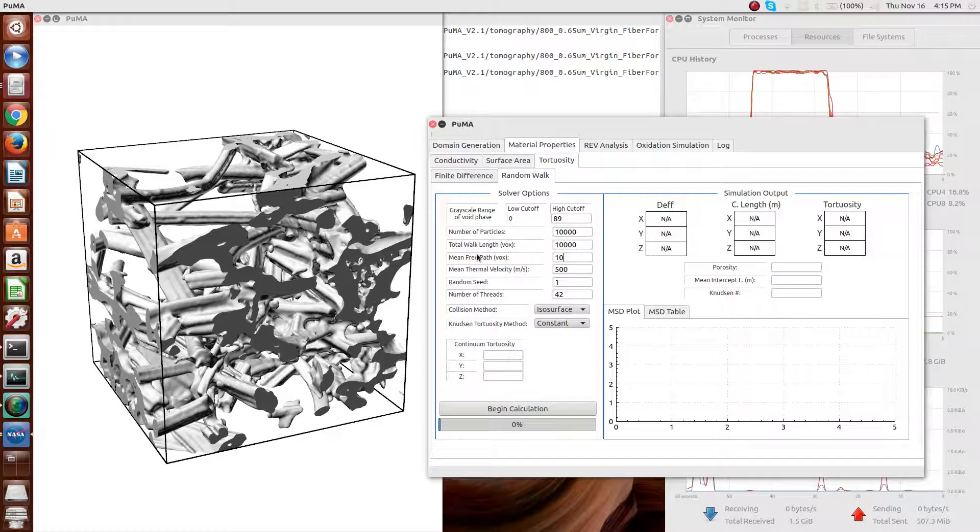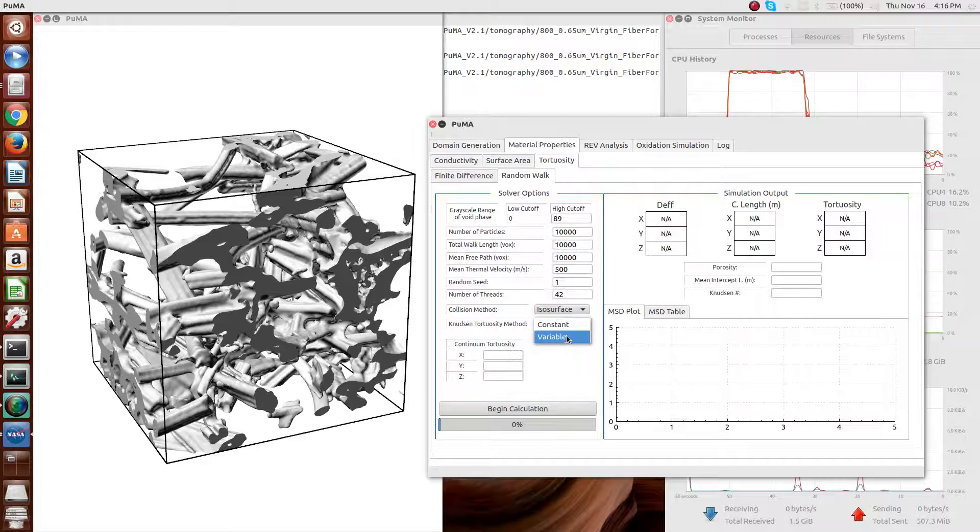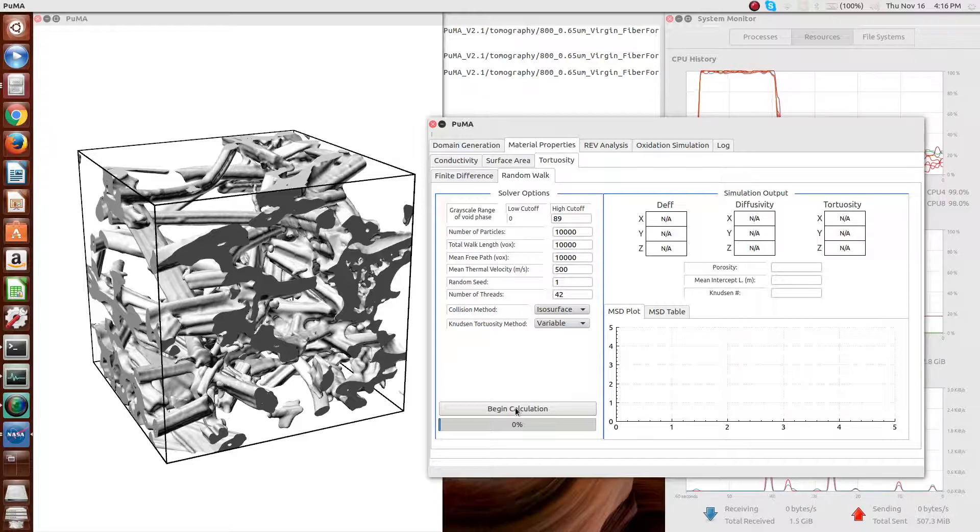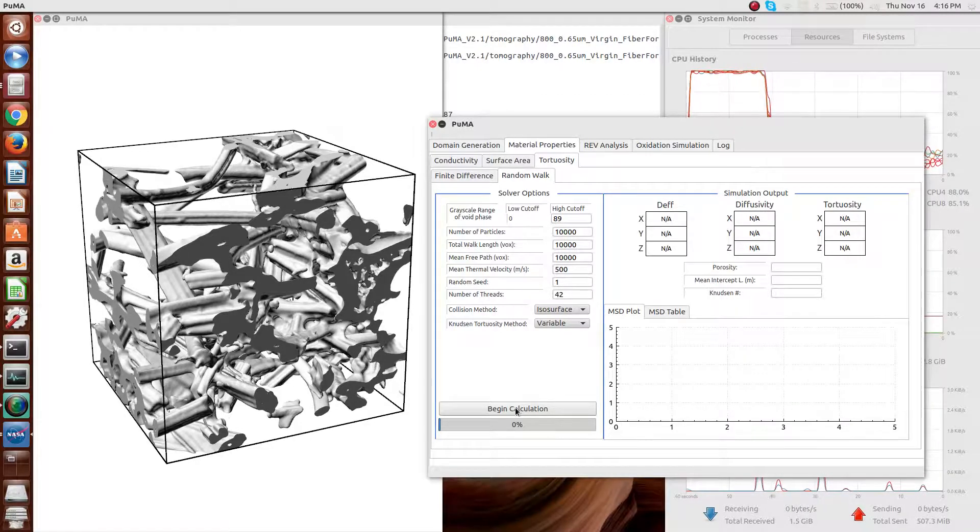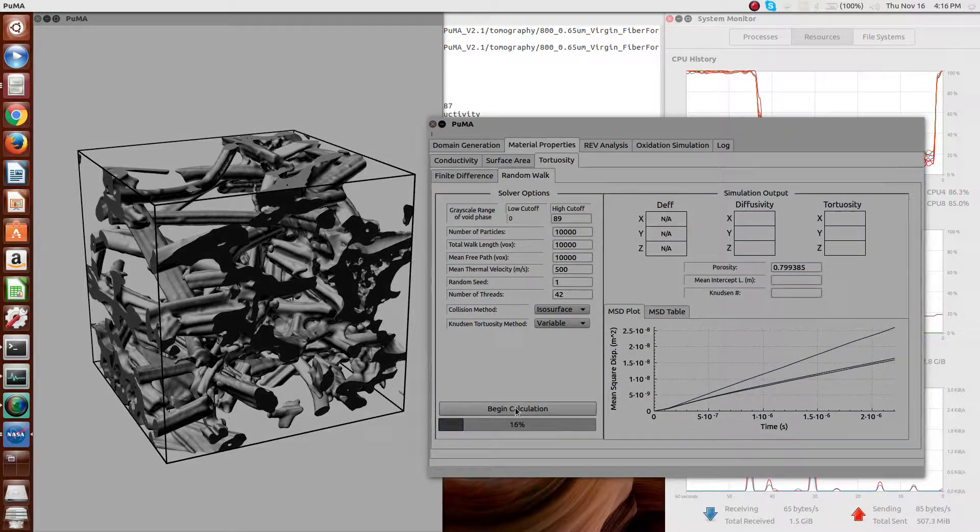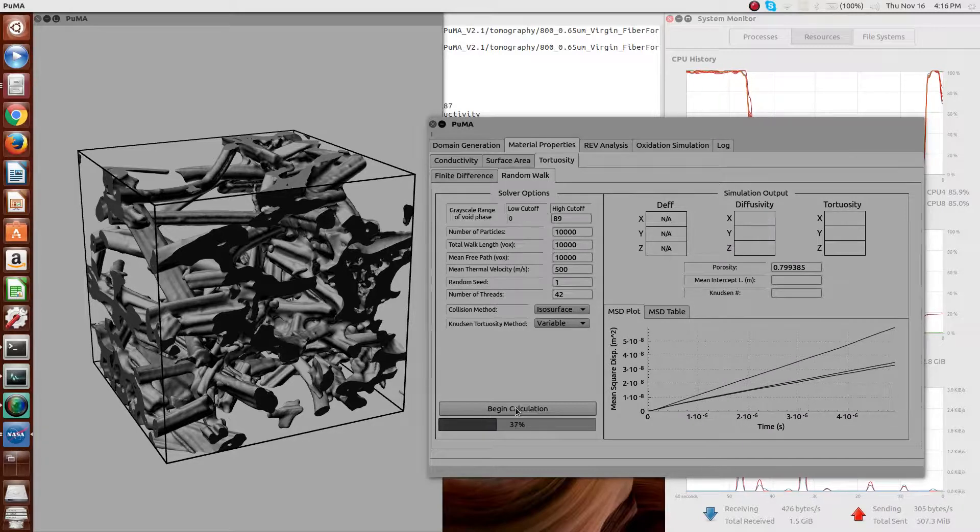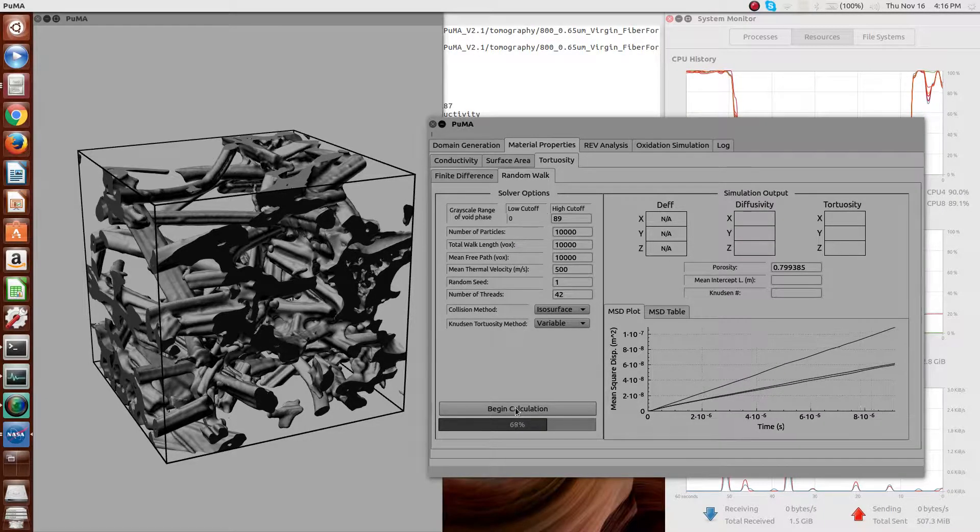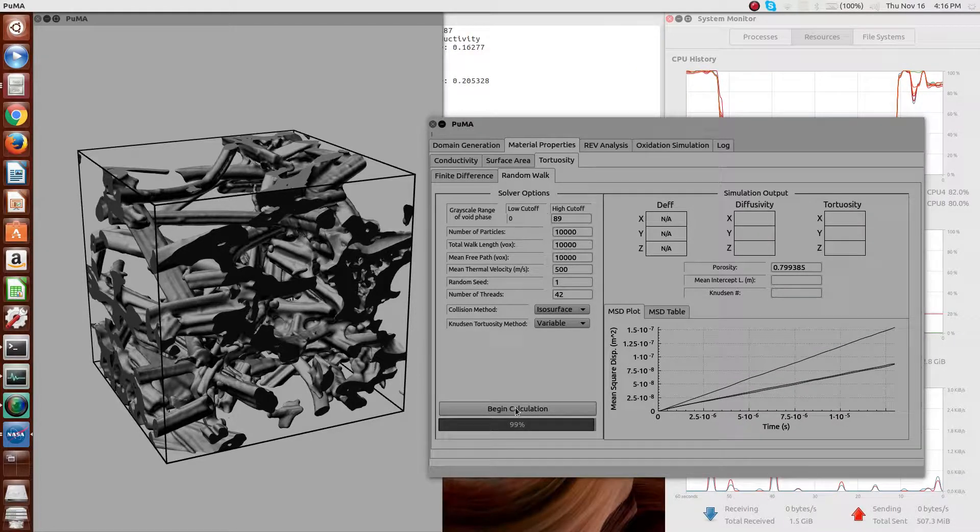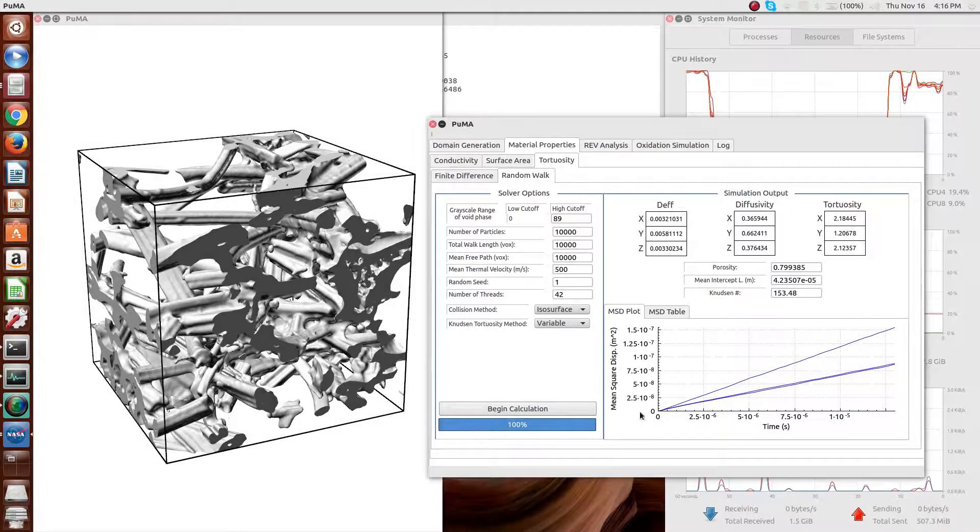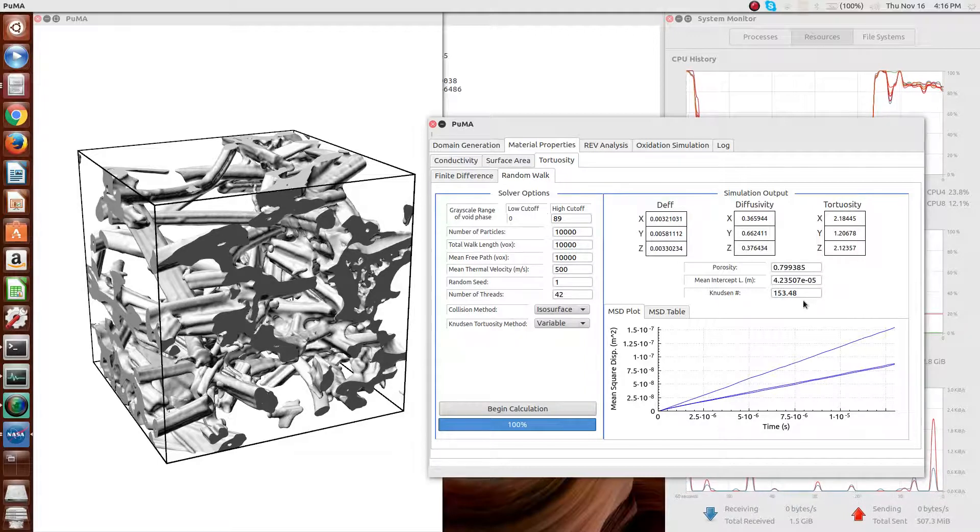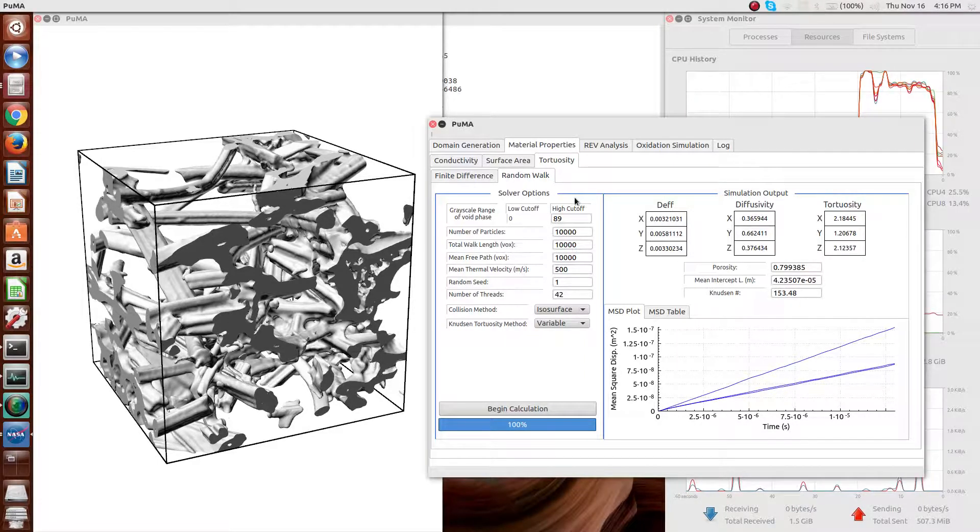In this case, we vary the mean-free path to impose a large Knudsen number, and we can solve for our tortuosity factor in the rarefied regime using a random walk method. In this random walk method, particles are placed inside the voids and diffused randomly through the materials. Whenever collision occurs with the surface, it is reflected diffusely, and eventually you solve to convergence and you get out your tortuosity.